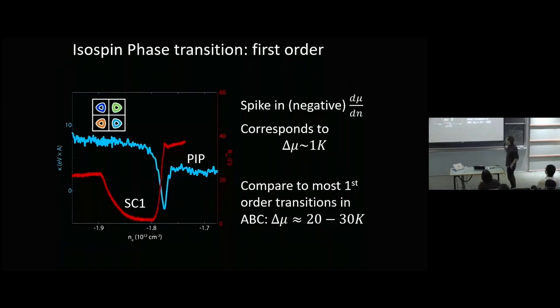Now, something we found out only quite recently by doing really careful thermodynamic measurements is that that phase transition is actually first order. What I'm showing you here is just a more careful measurement than we were able to do in the original paper. It wasn't clear originally whether this transition from the state that's superconducting into this other isospin polarized state is first order, but you can see this negative compressibility spike. That negative compressibility spike happens when you have a first order transition. You have two phases, they're crossing, and so the curvature of the free energy is going to be opposite sign when you cross, and that's how that shows up. And this is very well known from similar experiments, let's say, on fractional quantum Hall systems and so on. So it looks like you have a spike, a negative dμ/dn. It corresponds to a change in chemical potential of about 1 Kelvin.